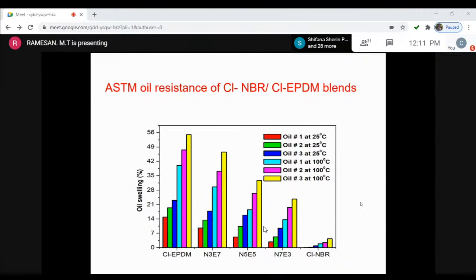And we have already published that chlorinated nitrile rubber has very high oil resistance compared to nitrile rubber. At the same time, nitrile rubber is easily flammable, but our prepared chlorinated nitrile rubber in this system does not show flame, it is not easily flammable. That means it has very good flame resistance. It has very high oil resistance than NBR, so this chlorinated NBR can be used as a substitute for nitrile rubber.